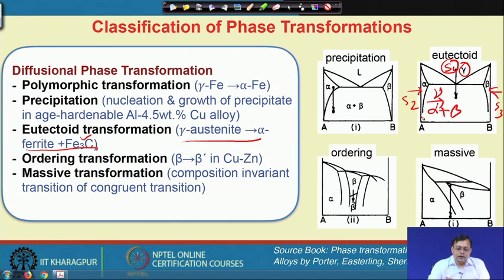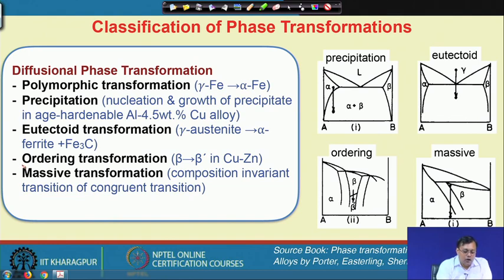Now, there are also other types of diffusional phase transformation that occur, like ordering. In ordering, there is not very long range diffusion required, but not like solidification. So, here beta to beta dash transformation, another example in the copper zinc system. If we choose a composition near 50-50 of copper and zinc, the copper zinc type system is shown here. From beta we will get an ordered phase which is beta dash. This dash actually represents that it is an ordered structure. So, a specific type of atoms, let us say the zinc atoms, occupy some specific site in an FCC or some other kind of structure. So, this is called an ordered transformation.